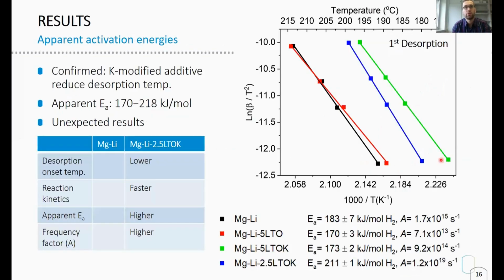In order to do it, I measured these samples with the DSC using Kissinger plots. It is seen in the first desorption reaction of the pristine sample that it has an activation energy of 183 kilojoule per mole. On the contrary, the activation energy value rises to 211 kilojoule per mole for the sample which has potassium modified additive.